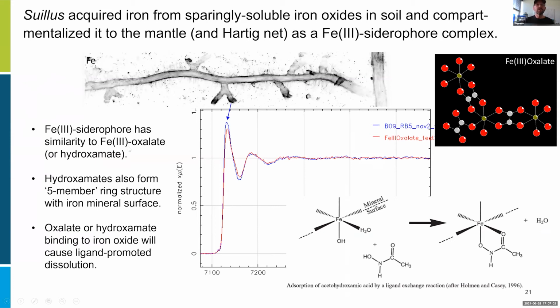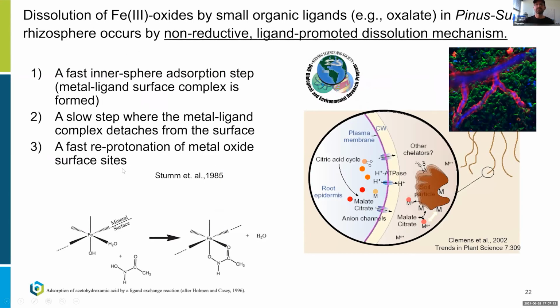It's very similar to iron oxalate or hydroxamate, but it's definitely some sort of small low molecular weight iron compound that stabilizes iron in this iron 3 oxidation state, which is kind of fun because we think we have evidence, and I'm trying to animate this over here in real time, that we have a ligand promoted dissolution mechanism that's not reductive. Again, this is not what we expected.